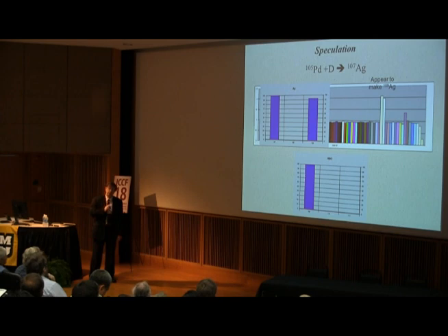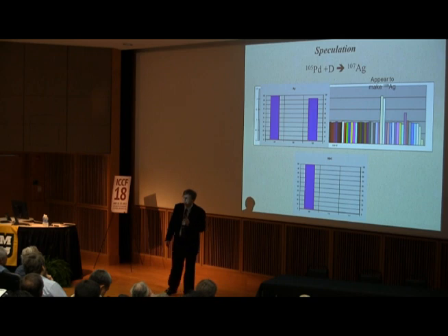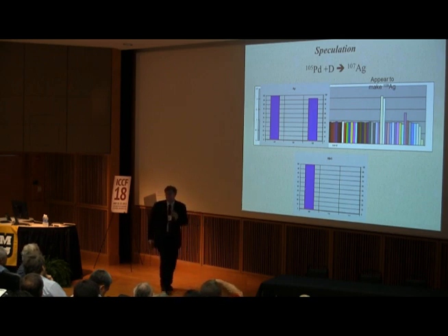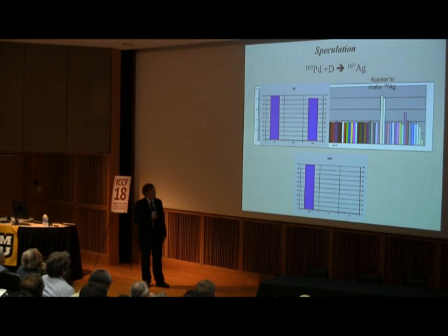We forgot one thing. As we're extracting the ions from this 10,000 degree plasma, they get colder. They can recombine. In certain metals, niobium, one of them, likes oxygen. So it recombines from that plasma, forming niobium oxide. If niobium is in that sample, we're going to get a small peak, down in the trace level because silver is not a lot of it there. And we misinterpret the 109 from silver as being an isobaric, meaning something the same mass, ion.